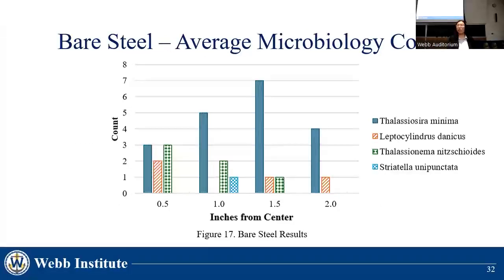The average quantity of microbiology observed on the bare plates is shown in figure 17 above, sorted by type. The x-axis shows the distance from the center of the plate, ranging from 1/2 inch to 2 inches away. The y-axis shows the count of microbiology averaged over the 2 identical test plates. 4 types of microbiology were observed on the bare plates.